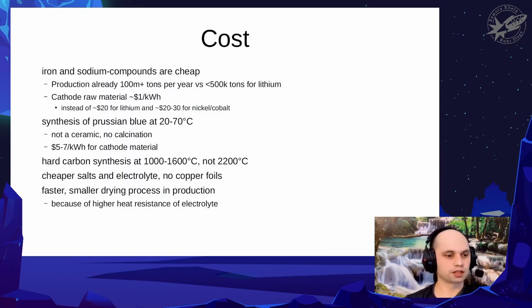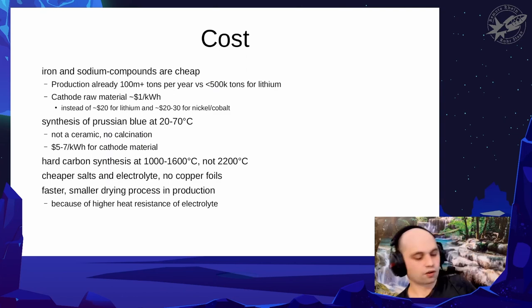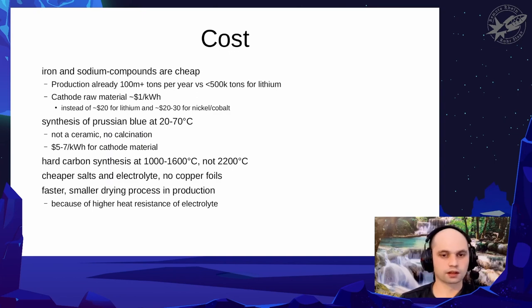Cost can be much cheaper, especially because the raw materials are so cheap. But it's not just the raw materials. The synthesis is also much cheaper because the layered oxides are ceramics. And if you know how to make ceramics, you know that you have to fire them at very high temperatures. If you have a cup like this, the ceramic would have to be heated up at almost 1,000 degrees Celsius to make this into a ceramic. But for the Prussian blue, the temperature you need is no more than the hot tea that I have here in the cup. And that I really need now.